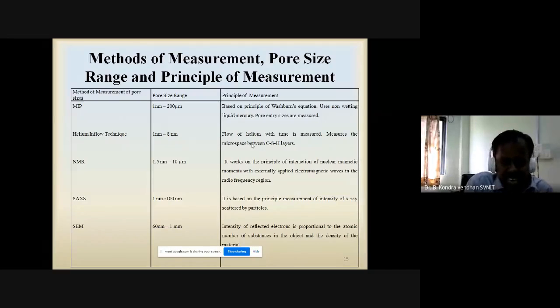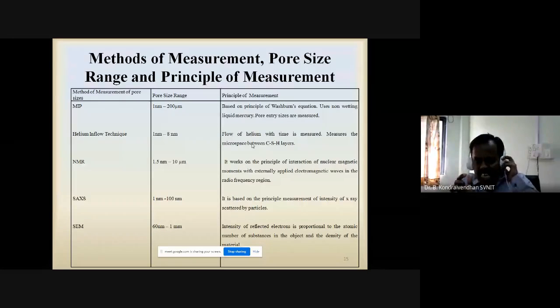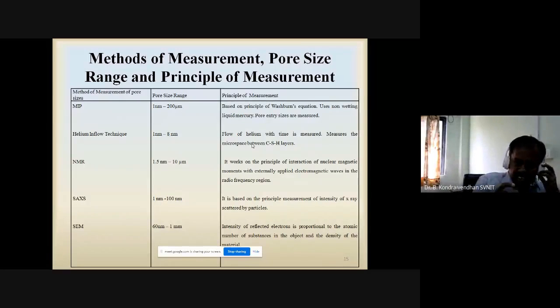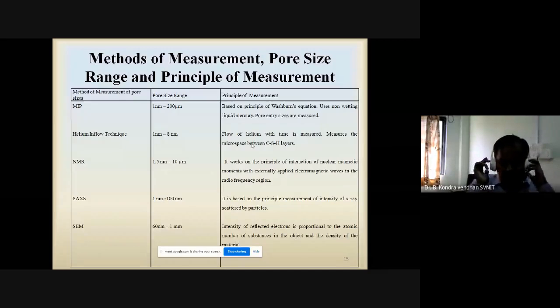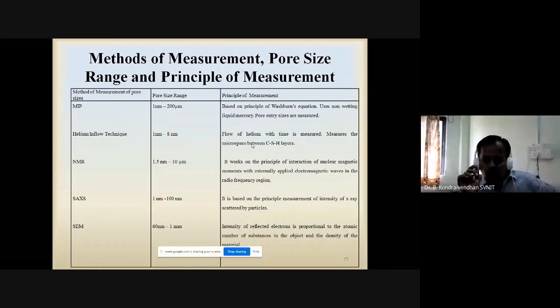Next, the helium inflow technique. It can measure pore sizes from 1 nanometer to 8 nanometer. The flow of helium with time is measured, and it measures the microspace between the C-S-H layers. Nuclear magnetic resonance can measure from 1.5 nanometer to 10 micron sizes. It works on the principle of interaction of nuclear magnetic moments with externally applied electromagnetic waves in the radio frequency region. And the small angle X-ray scattering method can measure pore sizes from 1 nanometer to 100 nanometer. It is based on the measurement of the intensity of X-rays scattered by particles.